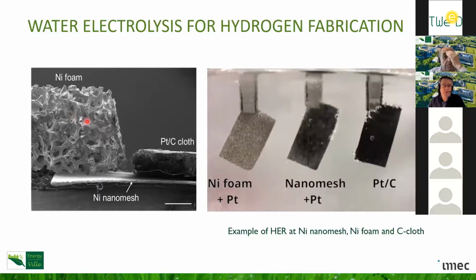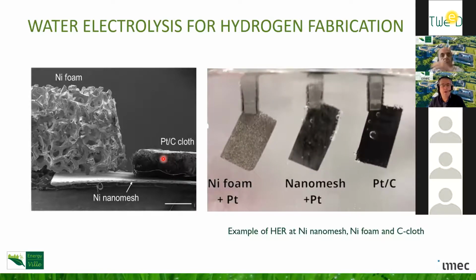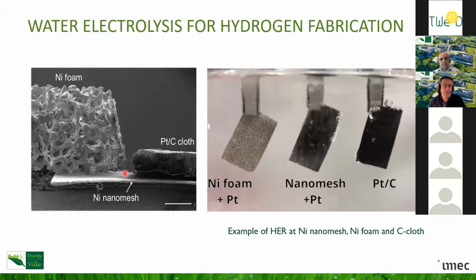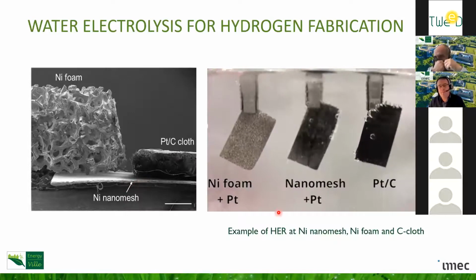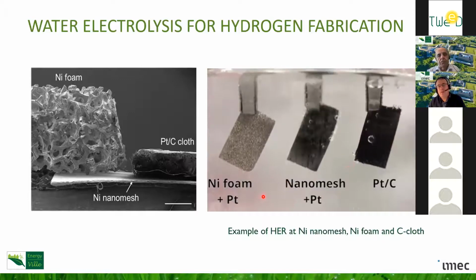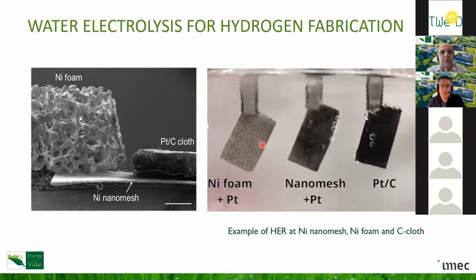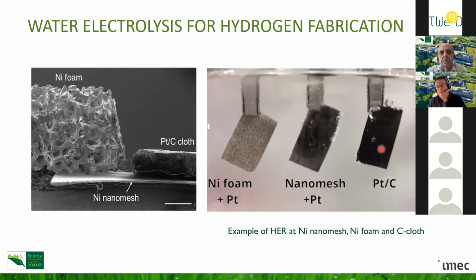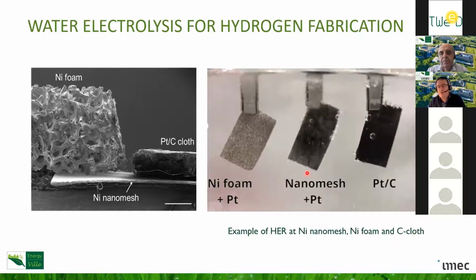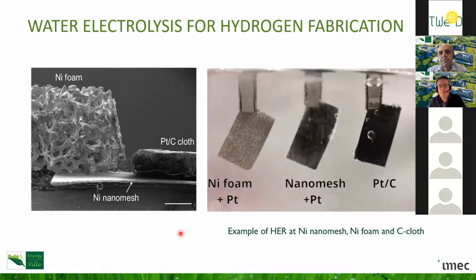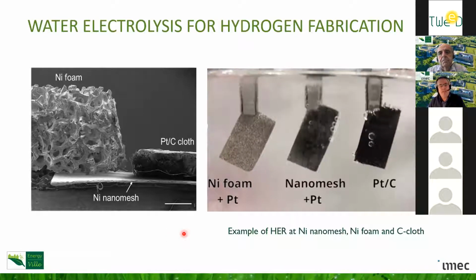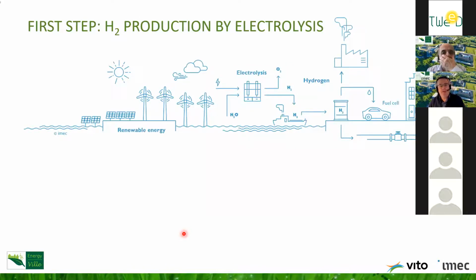Now, here are also different schematics. The nickel foam, platinum on carbon cloth is also sometimes used. We developed this nanomesh structure here, which can be very thin for a similar porosity. And you see these different materials producing hydrogen in this set of examples, where you have the nickel foam and the platinum carbon cloth, which bubbles a little bit. Our nanomesh structure is bubbling heavily, showing that hydrogen is really produced in this example. But this is the current step: we are developing this membrane electrode assembly using that nanostructure, being the core of the electrolysis system that can be used with renewable energy as source, producing hydrogen.